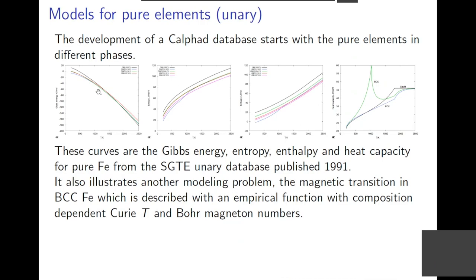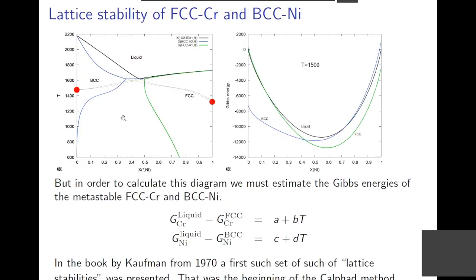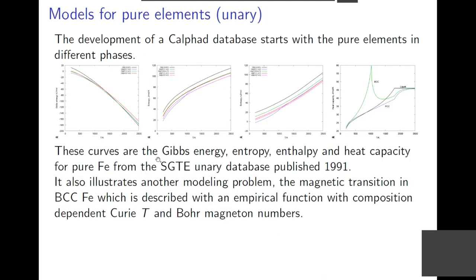But one thing is that using such linear temperature functions for the lattice stabilities means that you assume that the properties of the different phases for a pure element have the same heat capacity. And that works quite well for most elements. But it doesn't work for iron.